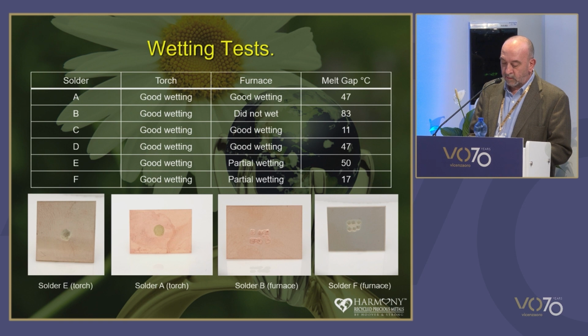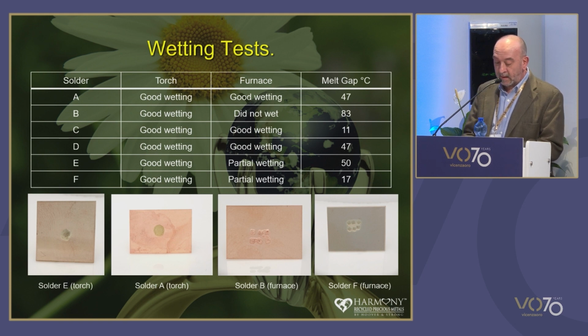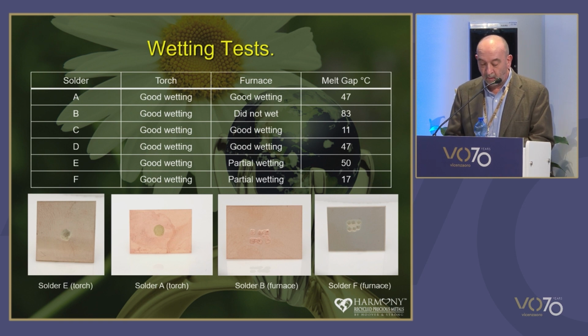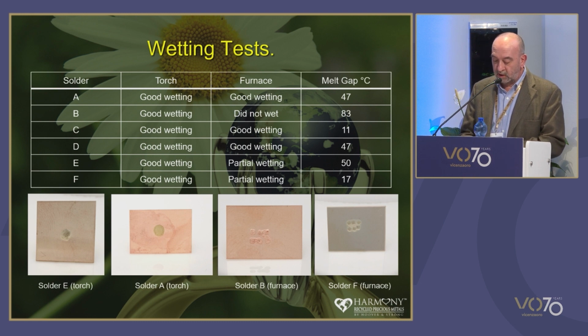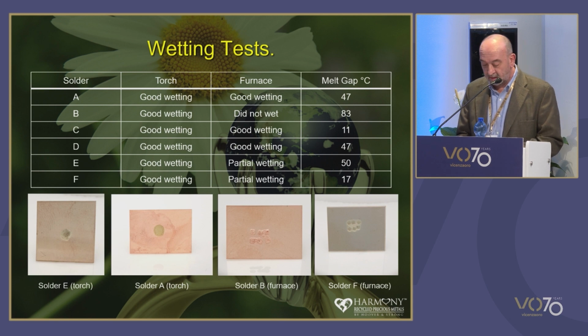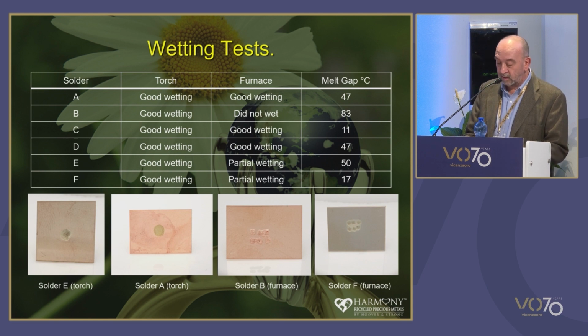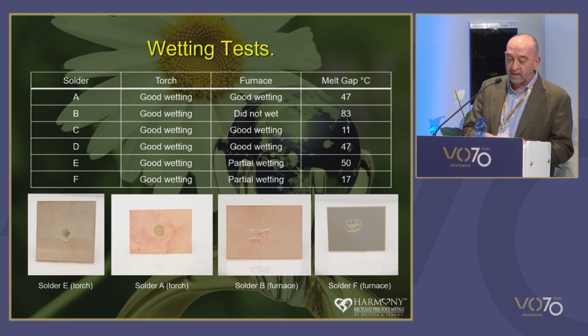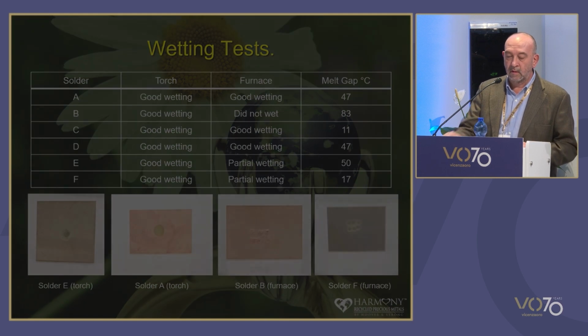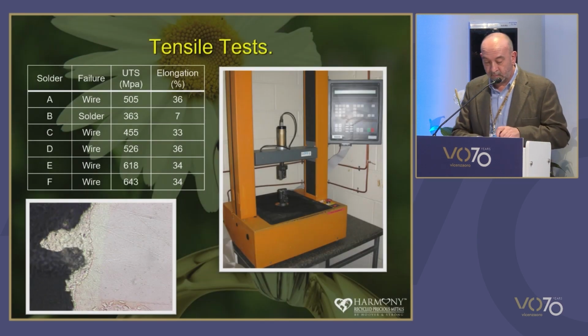Also note that the worst result was solder B, and it was the solder with the largest melt gap. So from these results, we can possibly say that the solders chosen are more sensitive to furnace conditions than direct torch. So after that, we decided to do some tensile tests.